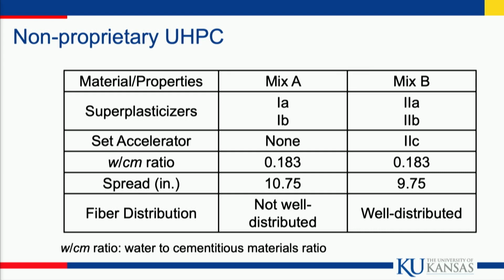We batched more than 100 mixtures to try to get the right mix down. We ended up with a mix A and a mix B towards the end. Two different sets of superplasticizers. One had a set accelerator, the other did not. Same low water cementitious material ratio. The spread was a little bit higher on mix A, but a key point is the fiber distribution. You need a good fiber distribution. It wasn't nearly as good on mix A as in mix B.